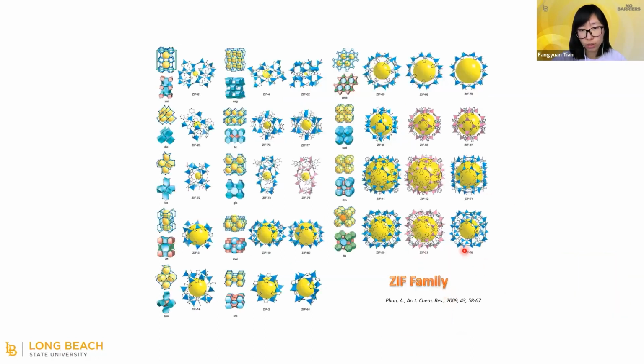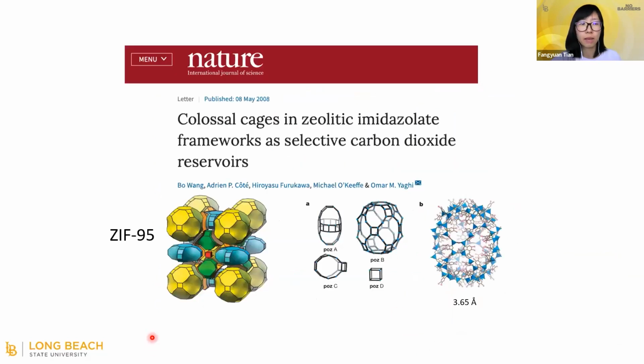We go back to this table and look at the whole ZIF family. And this time we noticed a compound known as ZIF-95. ZIF-95 has a similar but more complicated structure. It has a larger pore, and the aperture is around 3.65 angstrom.